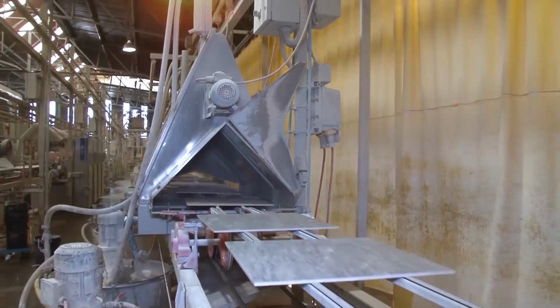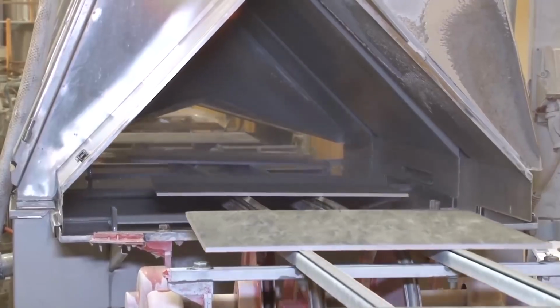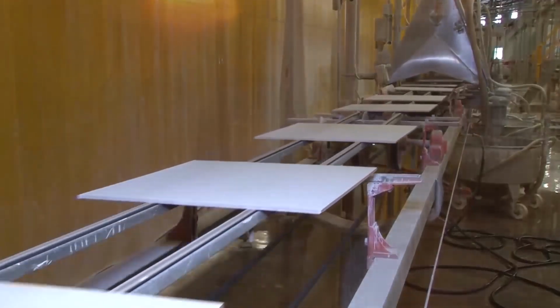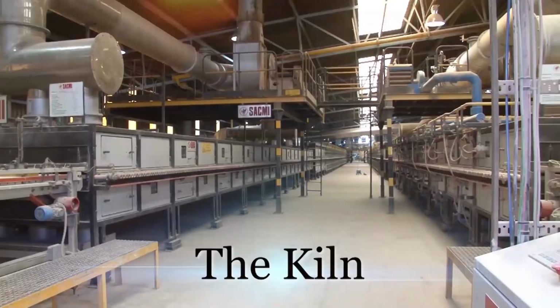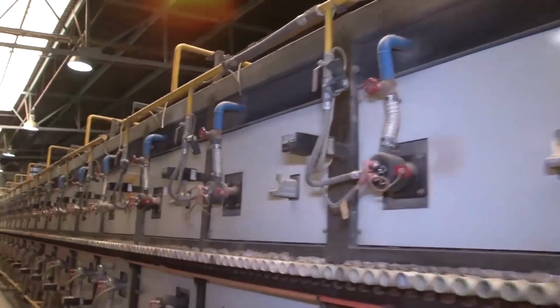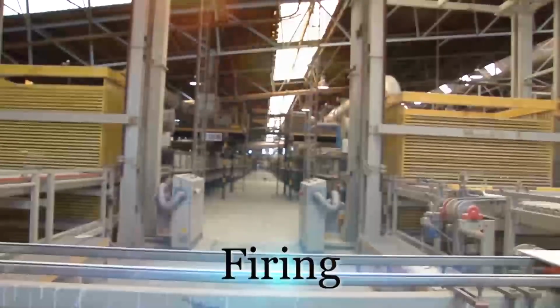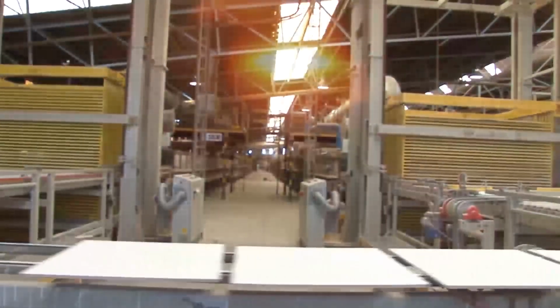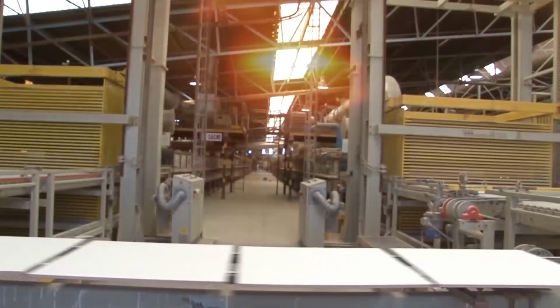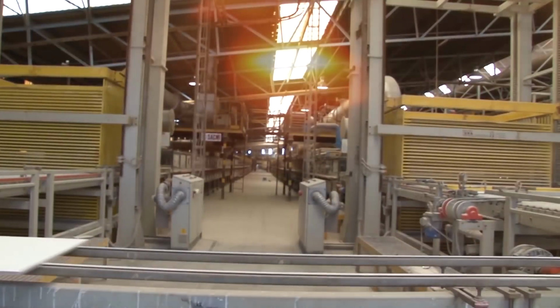A protective top coating of glaze is sprayed onto each tile. This turns white shortly after it comes out of the spray tunnel, but will become transparent as the tile passes through the firing process in the kiln. The kiln is a long tunnel heated by gas heaters, through which each tile passes in a process known as firing. In the first section of the kiln, the tile is dried at low temperature to remove water from the clay. If the tiles were subjected to very high temperatures in this first phase, the water in the tiles would turn to steam, and many of the tiles would explode.